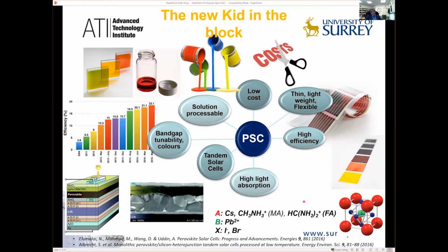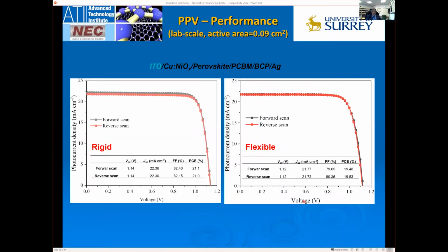We've also seen some very new materials that come on the scene, and quite a few groups within the UK are looking at perovskite-based materials that have lowered the cost even further. Within our lab also, when we start looking at perovskite materials, for example, if you use that triple cation system of methylammonium lead iodide based systems with formamidinium and cesium on ITO, on a rigid substrate such as glass, we can get 21% with very little hysteresis associated with it. We've gone beyond that and moved from rigid to flexible. And by moving from rigid to flexible on ITO, we can lose about 1–1.5% and still get suitable efficiencies here.